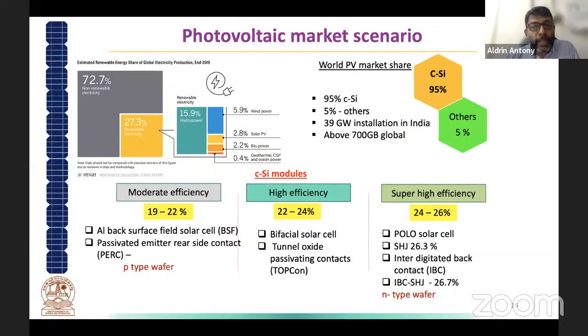So if you look into the market share, 95% of the market share is by crystalline silicon, and only 5% is by thin film. And if you compare the different efficiencies, you can think about three different types of crystalline silicon modules. One is of moderate efficiency, that is 19 to 22%. Initially there was the polysilicon or aluminum BSF type of solar cell, which I showed you earlier, that can have a maximum efficiency of 18%. But most of the modules which are being installed in Kerala recently are PERC, passivated emitter rear contact solar cells, and they have a moderate efficiency of 19 to 22%.